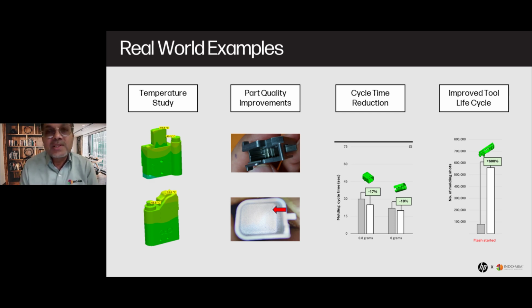Are we able to reduce the cycle time from 40 seconds to 30 seconds, or 30 seconds to 25 seconds, on a production basis, because now you are able to heat the mold and cool the mold more quickly than we were doing earlier? And most importantly, we also focused on whether there is a real improvement in the mold life.